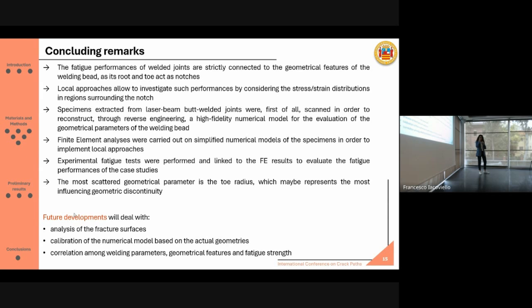What we noticed is that the most scattered geometrical parameter is the toe radius, both left and right radii actually, which may represent the most influencing geometric discontinuity. In addition, there was some, let's say, correlation between the geometrical data that we evaluated through the reverse engineering and the ones that are usually used, for example, in the notch stress approach.